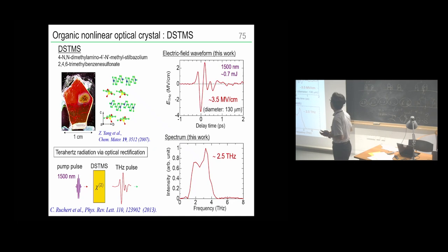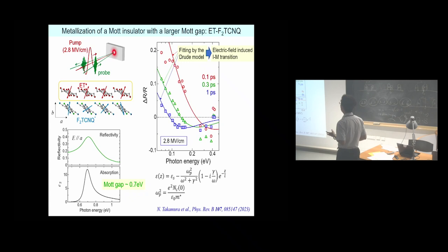Okay, more recently, an organic nonlinear optical crystal called DSTMS is also used to generate more intense terahertz pulses. This technique was developed by the Hauri group. Using this crystal, we also produced a strong terahertz pulse with an electric field amplitude larger than 3 megavolts per centimeter. And using this terahertz pulse, we investigated the metallization of a Mott insulator with a larger Mott gap.